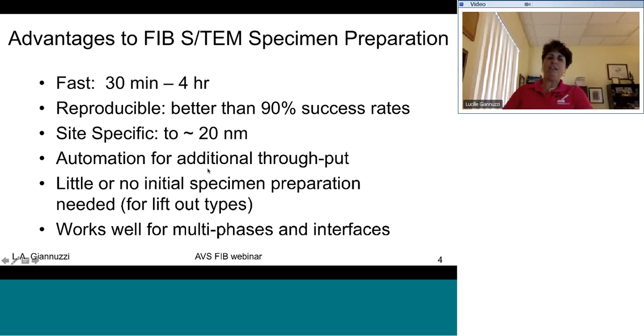So the advantage is that this is really very quick, somewhere on the order of 30 minutes to 4 hours, depending upon the sample type, the sputter yield of that material, and also the sample size. It's reproducible, with better than 90% success rates. It's site-specific to 20 nanometers or even less. You can add automation for throughput. There's little or no specimen preparation needed for lift-out types, and it works really well for multi-phases and interfaces.